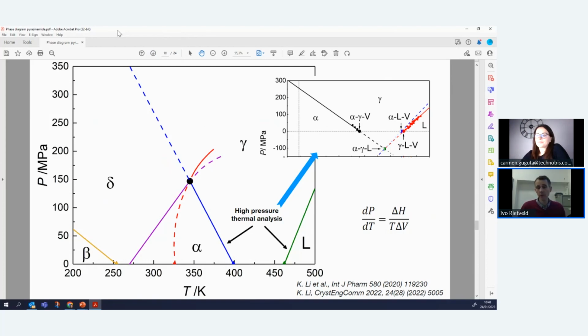In addition, we also did measurements that, again, we can do with colleagues in Barcelona, where we used high pressure thermal analysis. And on the right side, you have a little graph where we actually measured the alpha-gamma transition and also the fusion of gamma, so to say. Watch out, because in this scheme, there's also alpha-liquid, but that is a calculation that was put in this little graph on the side. So we measured the gamma-liquid transition and the alpha-gamma transition and could place them in this phase diagram. Also, again, specific for us, but it helps us to understand the overall point of view of the phase behavior of the system. If you can go to the next slide.